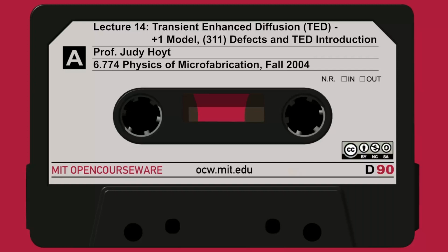Initially, this red line represents the initial +1 damage. So right after the implant is done, this is if you would assume you had this damage, this number of interstitials. So the interstitial density peaks here very, very high. After a microsecond, it's about the same. But look at it after a 1/10 of a second or a 100th of a second. We're talking about this flat profile right here. So after a 1/10 of a second at 750, we've formed all these 311 defects, and the interstitial concentration is now down to about mid 10 to the 12th or 10 to the 13th per cubic centimeter, according to SUPREM. And it's fairly uniform. Okay, let's think about that.